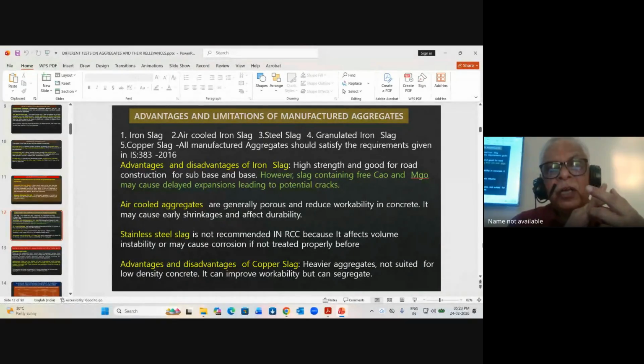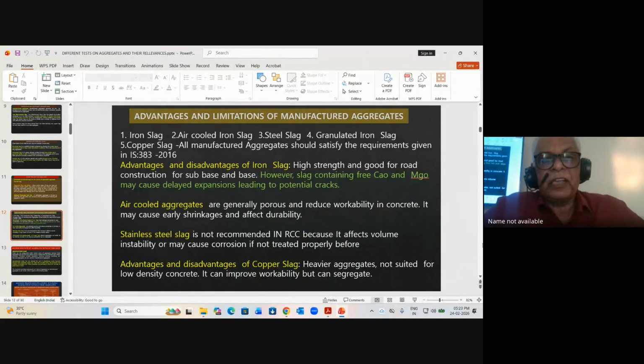There are some advantages and disadvantages of using slag in concrete. First of all, iron slag is high strength and good for road construction, for slabs, subbase, and bases. However, slag containing free calcium oxide and magnesium may cause delayed expansion, leading to potential cracks. This is a disadvantage of using iron slag. Air-cooled aggregates are generally porous and reduce workability in concrete. They may cause early shrinkage and affect durability. This is the negative aspect of air-cooled aggregates.